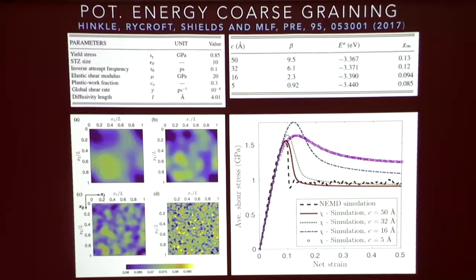Whereas when we choose the coarse graining too small, essentially there's so much noise in the system that we miss the important signature, or the important changes in the effective temperature over the local fluctuations, and we start to get stress strain curves that don't really reflect what happens in the MD.